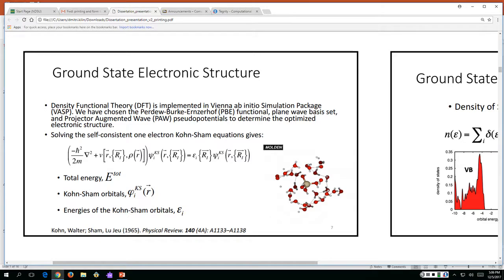So a couple things to note. We have a flattening of the bands as we take away this lead atom and the corresponding electrons, and we get an even flatter structure once we introduce these two charges back in. But the other thing to note is that we have this persistent vacancy state that doesn't change much as we change between different K points. So regardless of where we're calculating these energies, we're always going to find this type of structure. And so I think I'm going to remove this other picture here and just have it as extra information.